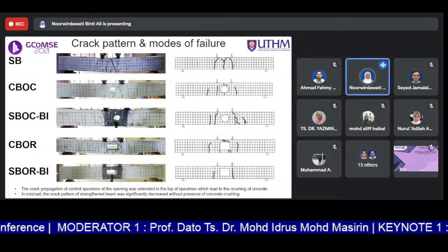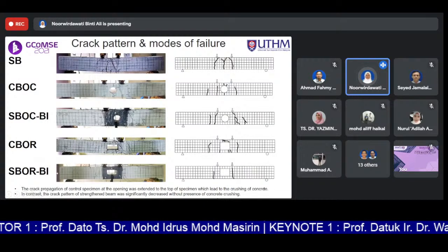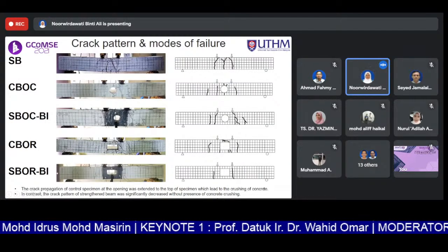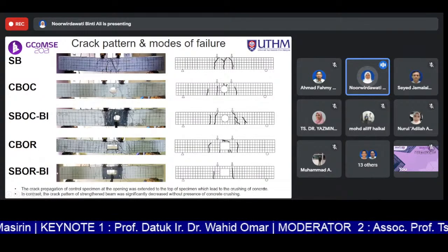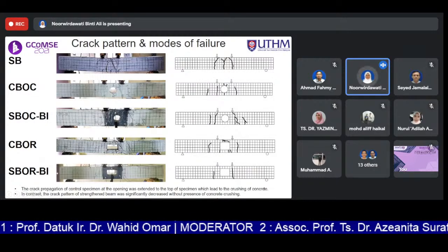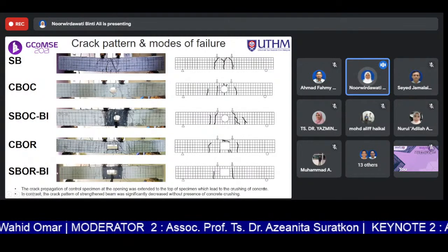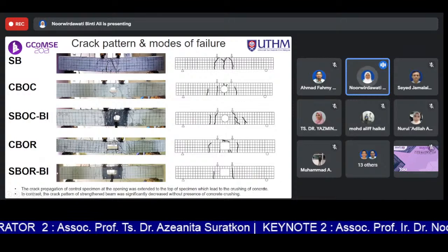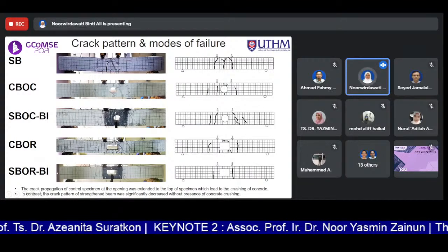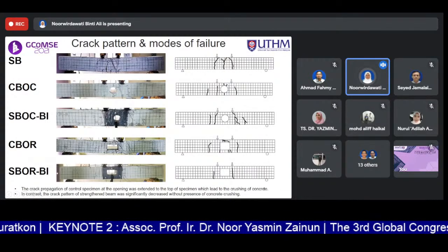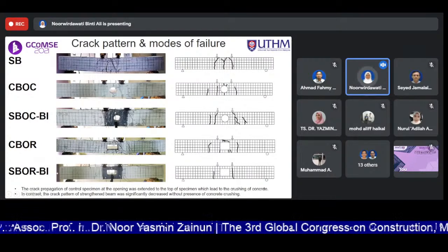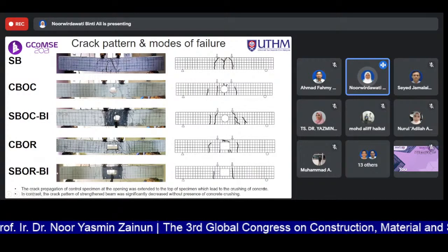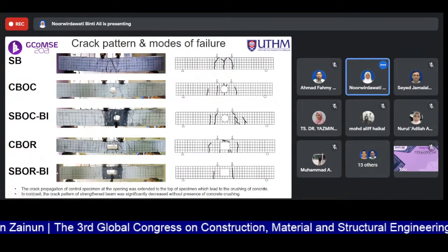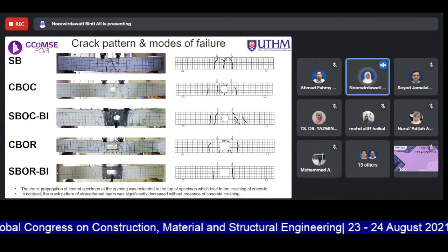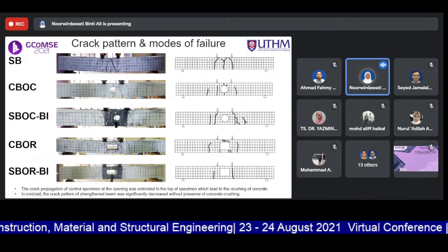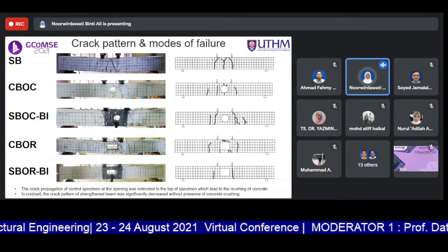But based on the beams without CFRP, we can see that at the opening there is a very big crack that can be observed. And this CFRP has improved the performance, where there is not much crack at the area, and no major or big crack observed at the area of the opening. So as the conclusion here, the crack pattern of the strengthened beam was significantly decreased, without the presence of concrete crushing.